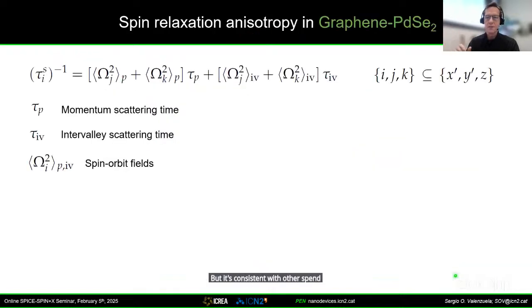Now, in regards to the Rashba spin orbit coupling, it was done by the group of Aires Ferreira, who analyzed our data. These peaks here are associated to the Rashba spin orbit field, which does not influence the spin Hall effect. And what they did is to demonstrate that this is of the order of 30 milli-electron volts, which is much larger than what you would expect. And this is something that we don't understand yet, but is consistent with other experiments that have been done with quantum Hall effect and so on.